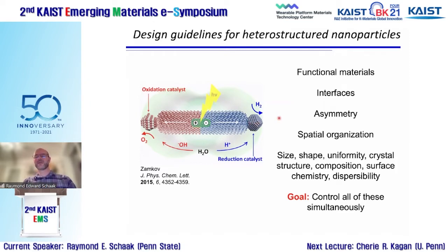It's interfaces that are robust enough to facilitate charge transfer. It's asymmetry. In this particular construct, you need directional migration. You need the charge carriers to move away from each other and not recombine. You need the different catalysts on different ends. The spatial organization matters. If you want to maximize what this drawing represents, you need to control the spatial organization at a very high level.